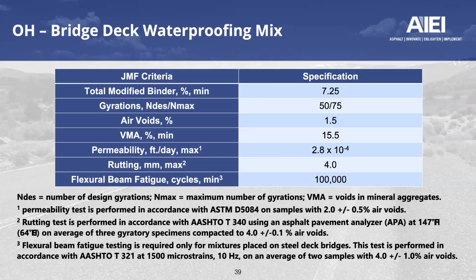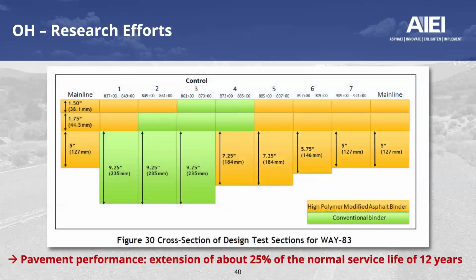They also have a flexural beam requirement, which is identical to what we saw in New Jersey, 100,000 cycles at 1,500 microstrains, with the specimens designed and built to 4% plus or minus 1% air voids. There is research that's going on in the state of Ohio